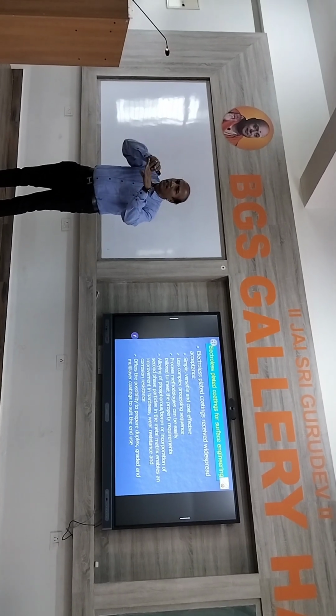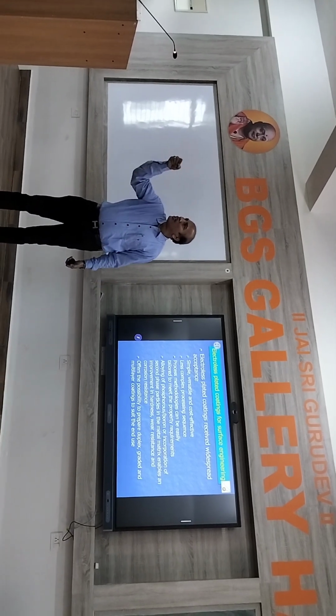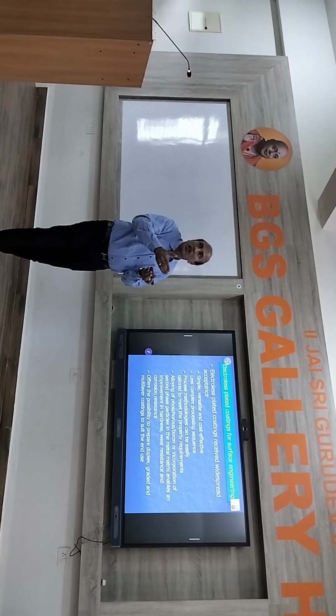For example, I want a top hard coat, and at the bottom, after some time, a corrosive environment is there, even if some pinholes or pores are present. At the bottom I have a thickness of maybe 20 microns of high phosphorus coating, so that as a duplex coating it gives both purposes, protecting the substrate, maybe mildly. Graded coatings: here also I will modify the bath in such a way that the reducing agent addition is slowly increased. Initially it will be low concentration, and periodically I will add it so that from the interface to the surface there will be a variation in the concentration of co-deposited phosphorus or boron. That way also it has other advantages. A variety of coatings can be deposited by this particular method.